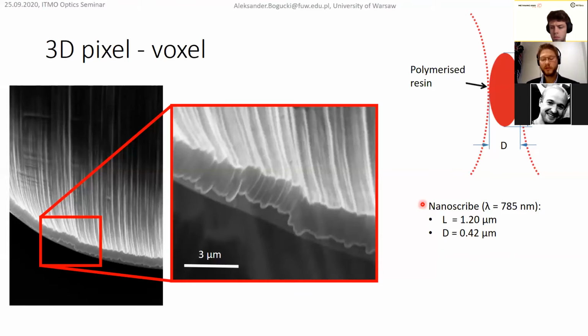But what is quite important, the resolution could be better. So if this is the smallest volume that can be polymerized, however, when you move more precisely, if your piezoelectric stage, for example, has a movement of 50 nanometers, then you are just moving this ellipsoid by 50 nanometers and then obtain smoothness on the top of it in this range. So even though this voxel is not so small, you can obtain very smooth surfaces. And especially there are a lot of techniques that can improve smoothness, like annealing or reflowing, or using some chemicals to make it even smoother.